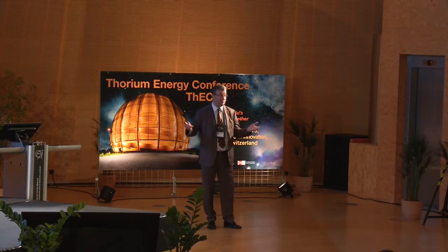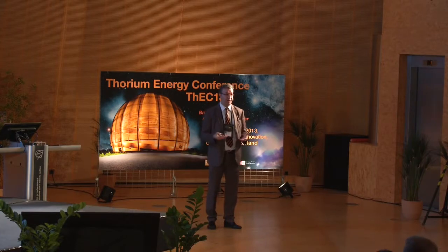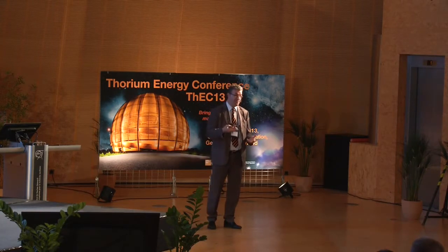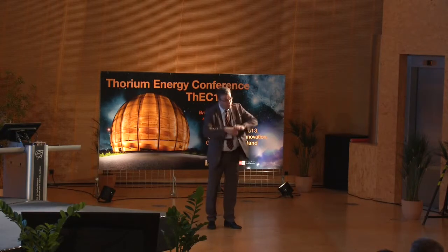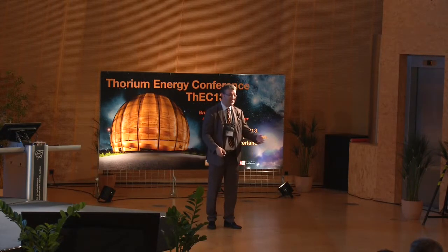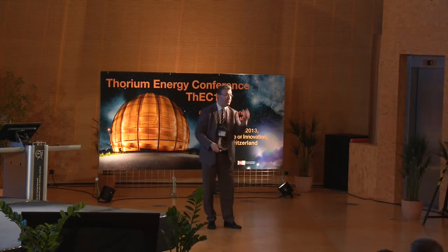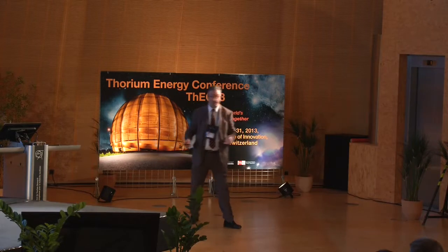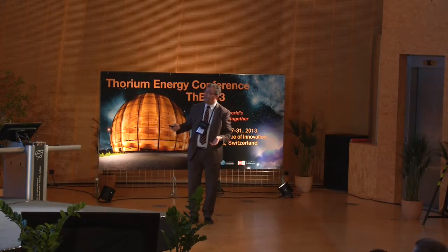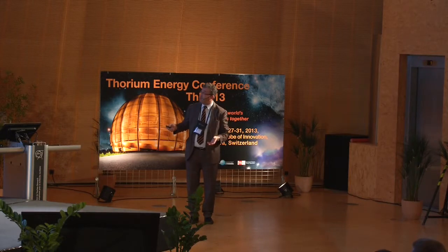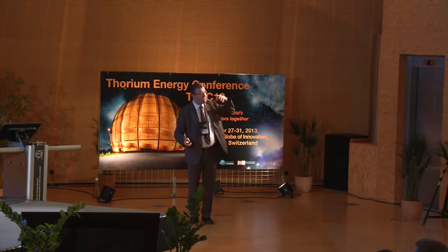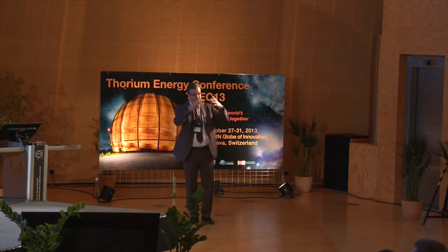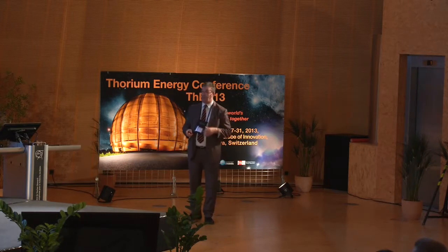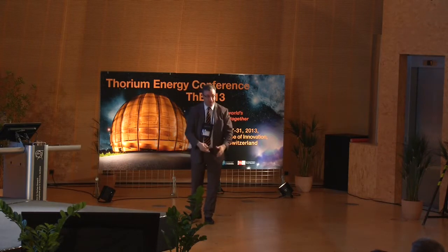Why? Because lead, or lead bismuth, is a very dense metal, so it's heavier than what you are putting in it. Instead of pushing all those elements and holding them there, just let physics work for you. Put them from underneath and they will be floating by buoyancy, they come into position. And so that's what we did. But nevertheless, the safety rods, those three guys here, they fall in the reactor by gravity. So they are with a ballast made of tungsten, and they can then drop even in the lead bismuth, and we are testing what is the time to get them in the system.